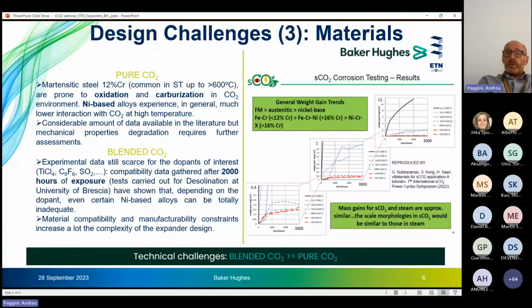The last topic I wish to talk about is materials. It's well known that martensitic stainless steel material, 12% chromium, which are materials extensively used in steam turbines up to temperatures well above 600 degrees C, are prone to oxidation and carburization in a high temperature CO2 environment. There is not an exact threshold above which the usage of martensitic steel in CO2 is forbidden, but there is a consensus that the switch to other materials should take place at temperatures lower than in steam.